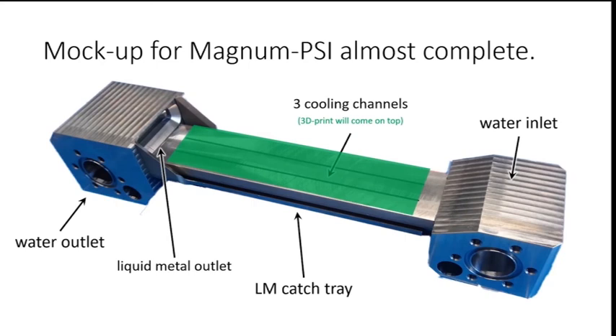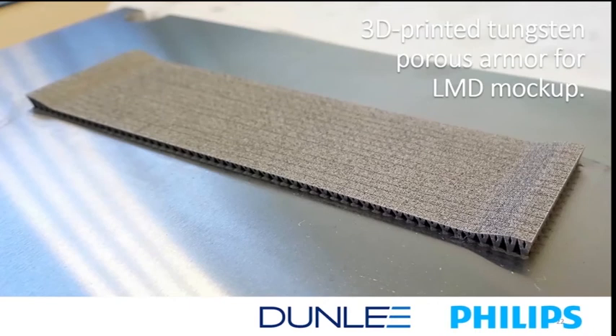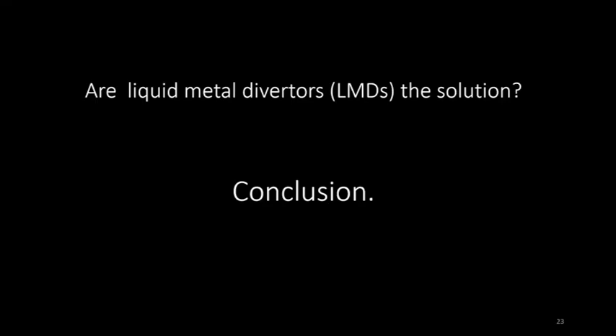And the reason that we put it in steel is just that we have to demonstrate the concept first, also with the flowing liquid metal. And the next step will be to make it out of the really high performance heat sink materials, the fancy copper alloys. And then finally, I wanted to end with this fantastic picture of the CPS, of the 3D printed tungsten, which is being made with Philips and with Dunlee. They did this test print on a steel slab, and the real texture is being printed as we speak on the actual mock-up.